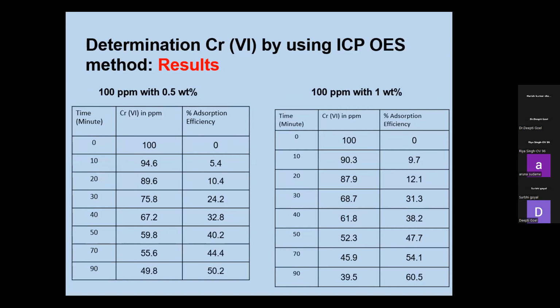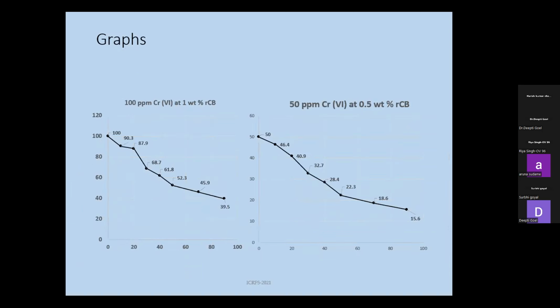Now these are the results we got for 100 ppm, and we can see here a comparison of 0.5% and 1% weight. So here we can see that for 1% weight, the percentage adsorption capacity is 60.5. Now actually after this, once I got this result, I did another activation of this activated carbon with KOH, again with impregnation, and I got a very good result, and that result is around 80% adsorption capacity.